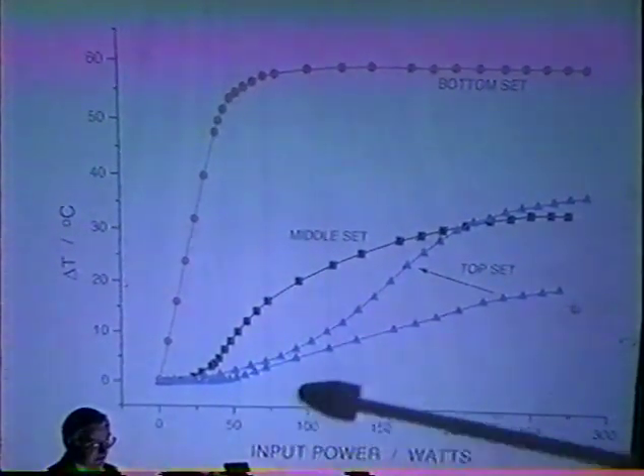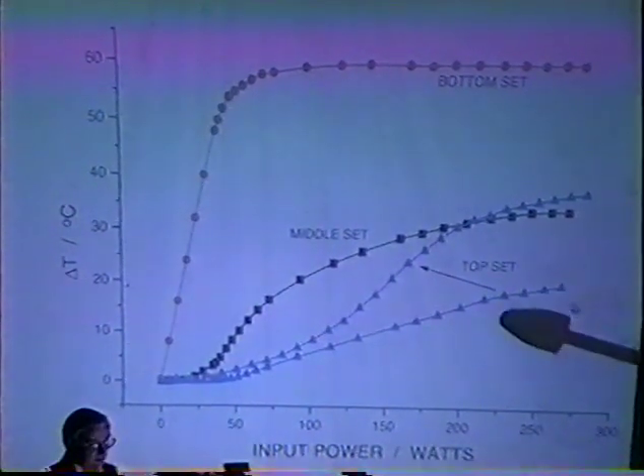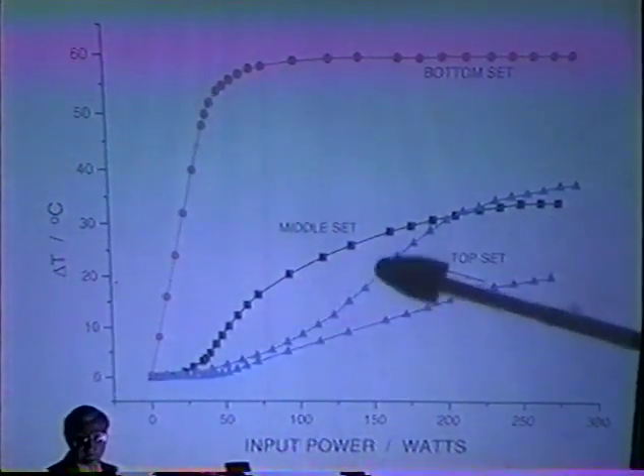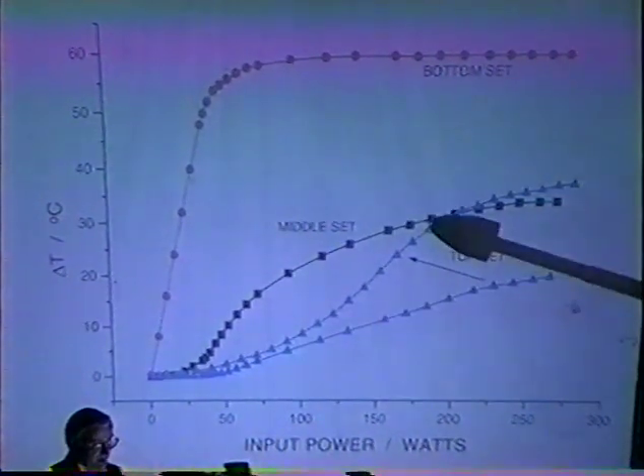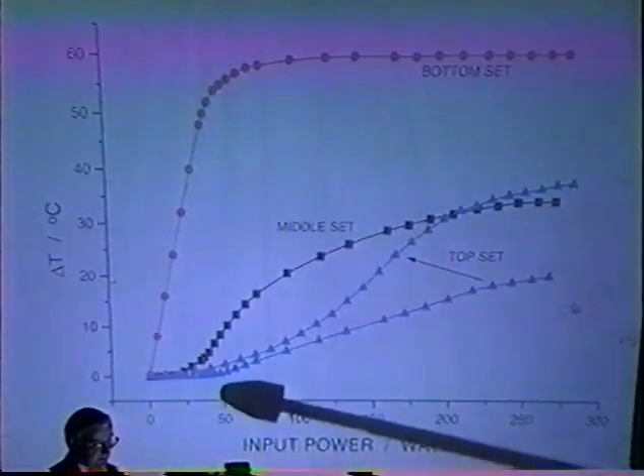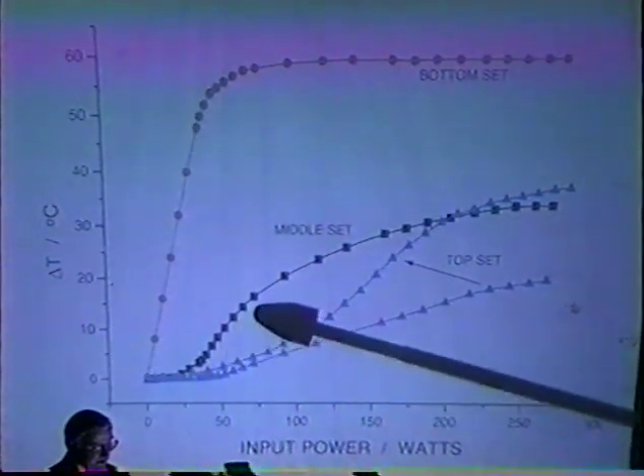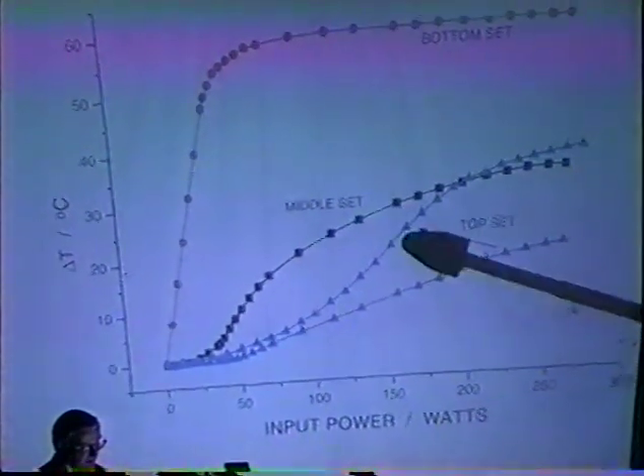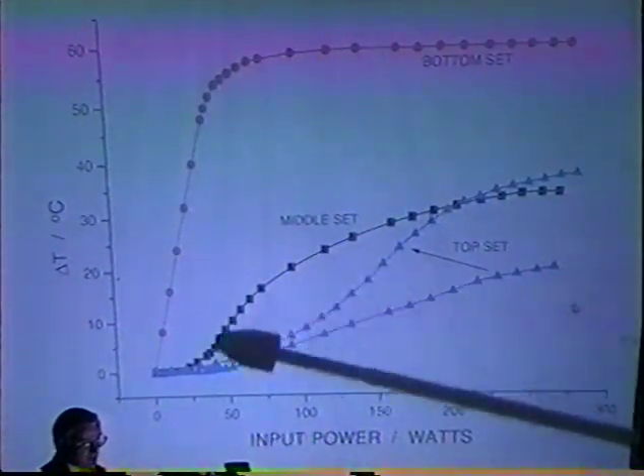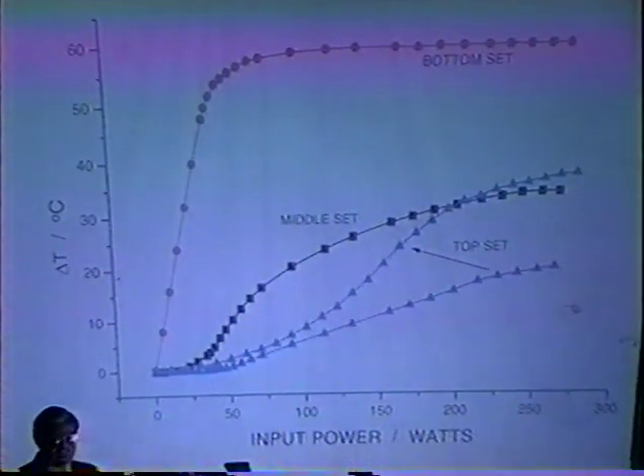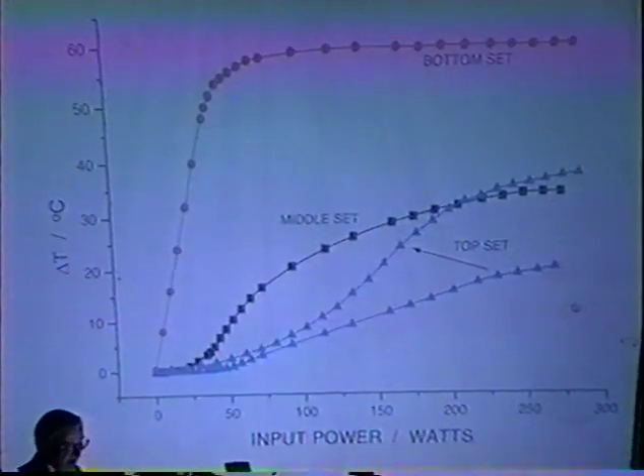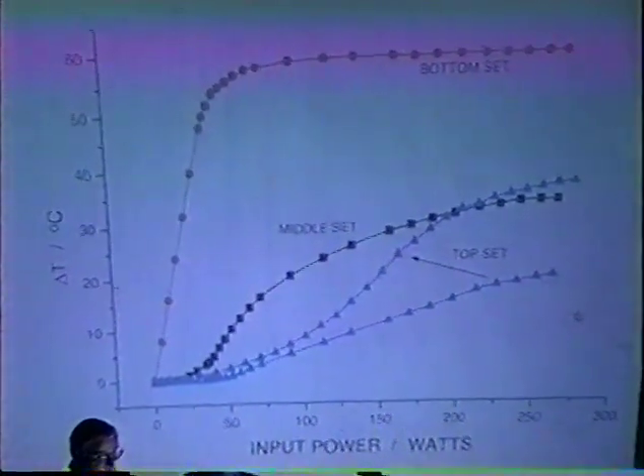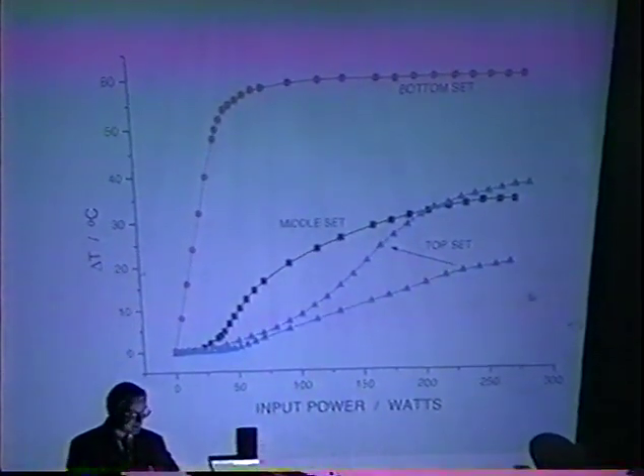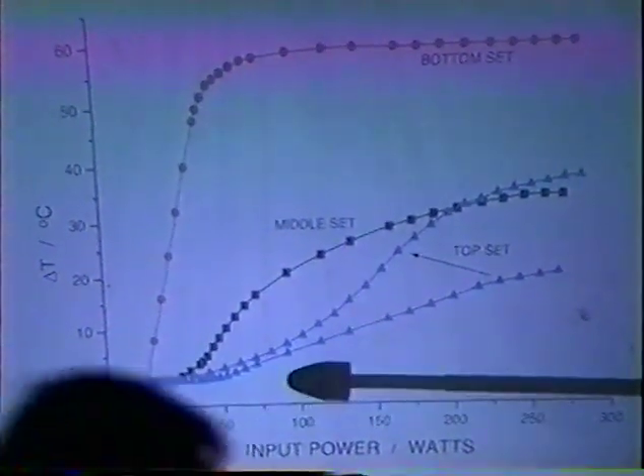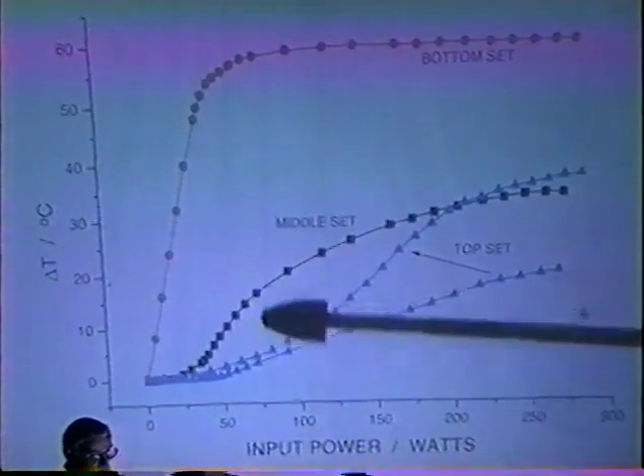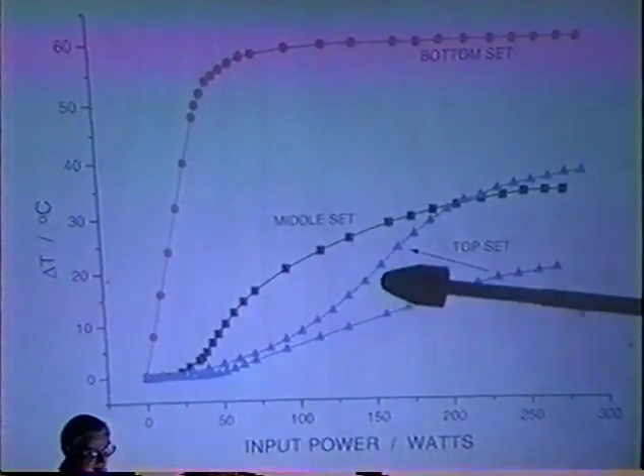In other words, for instance, for the top set, if you're working at low power, you may want to shift it back in this direction so you can look more accurately at the top set with respect to the middle set. You have your maximum sensitivity for the middle set in this region, and the maximum now in this region. They're closer together, so you can use comparison of these thermistors to get more accurate and confirmatory results between the various sets of thermistors. So the point is, you can change the lag time, or the onset of rise in temperature. You can change the sensitivity.